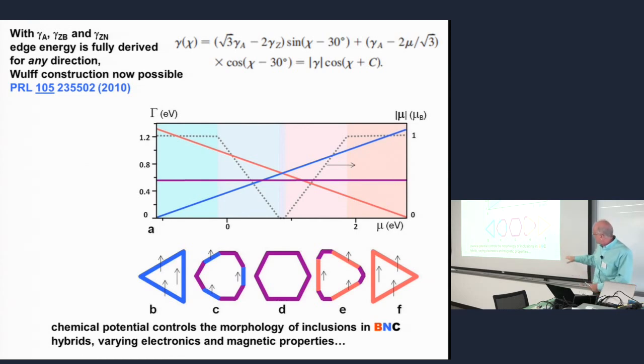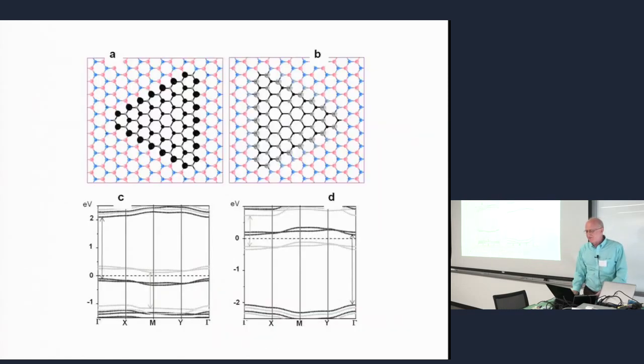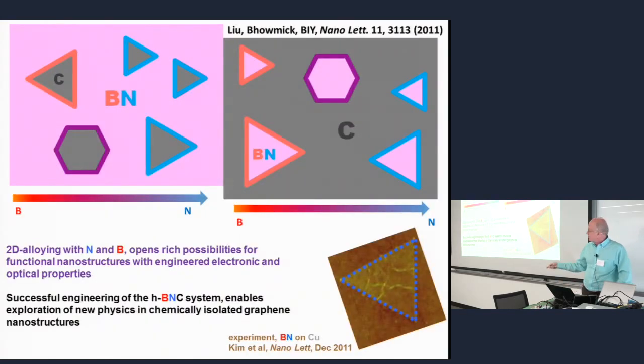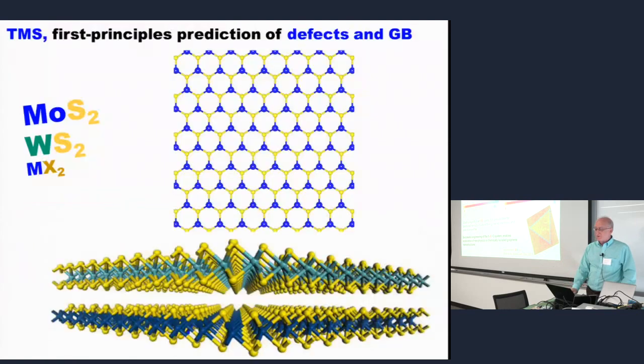So we were interested specifically in BN inserted in graphene. And that's what you get, these quantum dots. I don't go into electronics, but they can have different shapes depending on conditions at growth. And that's how chemical thermodynamics couples into the shape and the edge structure of these inclusions, and then, of course, into electronics. So this is a picture that illustrates it. So you have BN, you can have these shapes, all is well defined, they're not random, depending on thermodynamic conditions here. Or you can have these shapes. And what is in experiment, at least one example I show you, this is a nitrogen terminated triangle, so this falls into this category, but there are also observations of truncated and different shapes, and now we understand why.